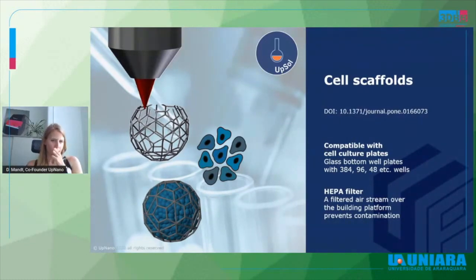Also for us, it was important that the system is equipped with a HEPA filter system. So we have a filtered airstream above the building platform, which prevents the contamination, for example, with dust, as dust particles are often bigger than the structures we are actually printing. When the system is open, we have clean room conditions of 1000, and when it's closed, you have no particles, and we fulfill clean room 100 requirements. The HEPA filter is on the whole time, so while printing and also when opening up the system, and therefore ensures that everything is clean. This approach is, for example, done with the UpSol material, this organic and inorganic hybrid material we are offering.